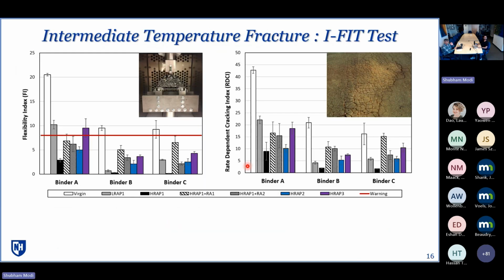Then coming to the intermediate temperature properties side, we conducted the I-FIT testing, and here the white bars are showing the virgin mixture results without any recycling agent or RAP in it. And here we can see that inclusion of the RAP clearly negatively impacted the results.